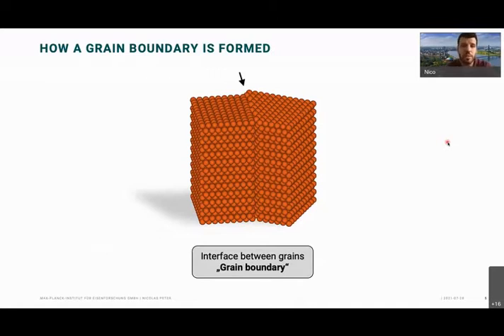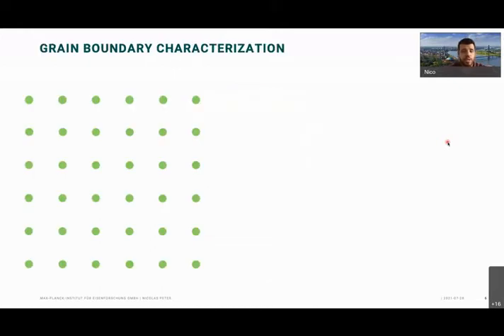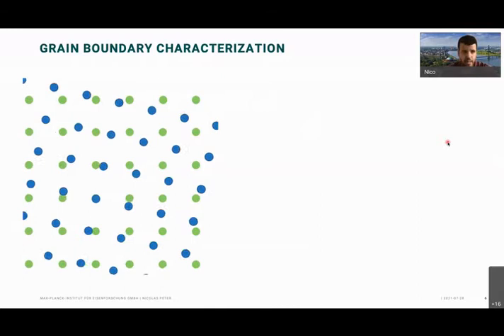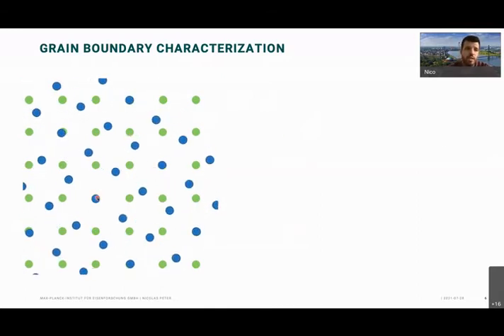How do you characterize grain boundaries? Maybe a little introduction to that, so that we are all on the same page. If you take a geometric approach, which is pretty common for grain boundaries in literature, you take one crystal lattice, put a second one right on top of it, and then rotate them against each other about this point. You will see that at certain rotations, you start forming coincidence site points. So what you form is these red points here. The green and the blue are the same position in this case. And this lattice is then called the coincidence site lattice, the CSL.